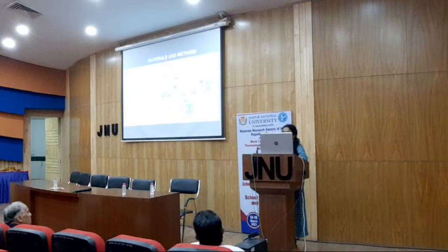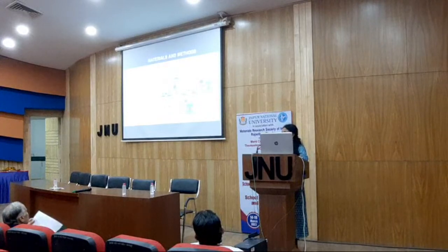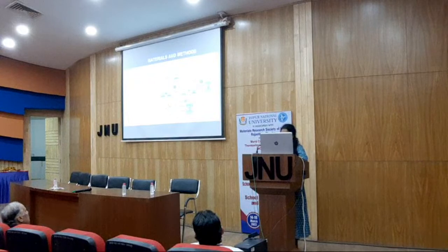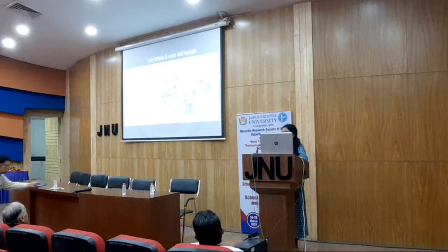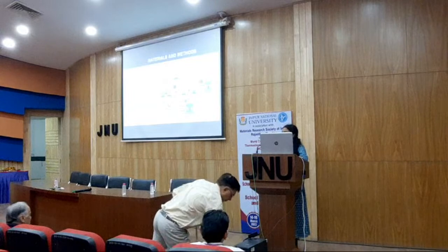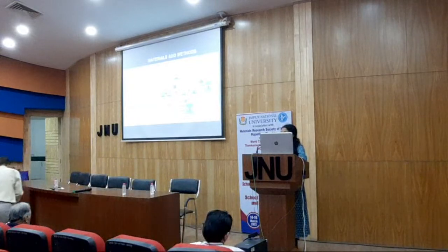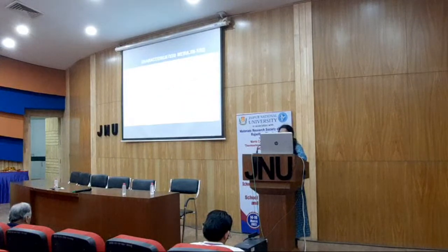And scouring has been done to remove the unwanted materials from the cotton fabric which is available in the market, and then the precursor solution was prepared, and then seed creation was done, and then the growth of it. We tried four different samples, where in two samples boron was used as dopant and in the other two boron was not used. The samples in which boron was not used were made for comparison.